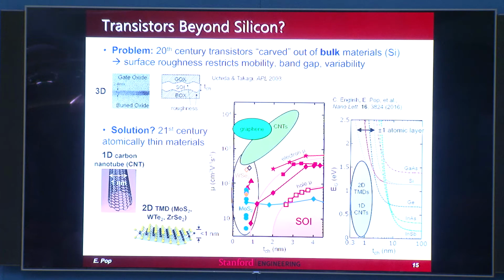And the reason this happens is because these materials don't have dangling bonds. They don't have rough surfaces, essentially. They still suffer from remote phonon scattering if they're embedded in dielectrics. So that stuff is not going to go away. And of course, we need to worry about that and screening and so on.